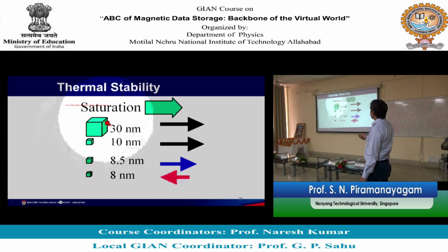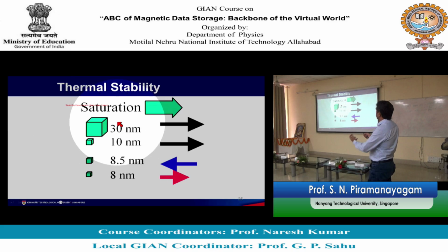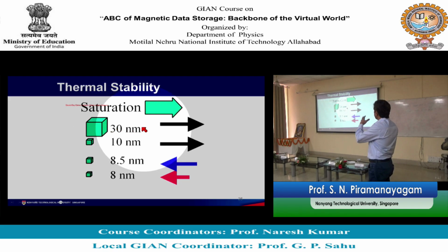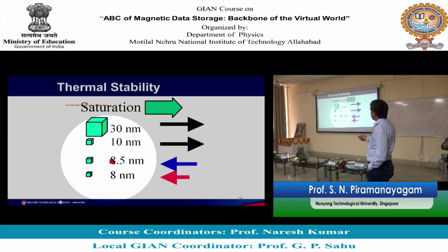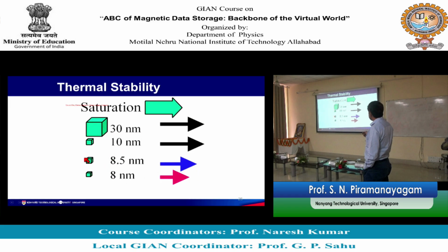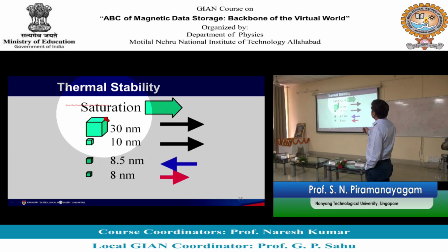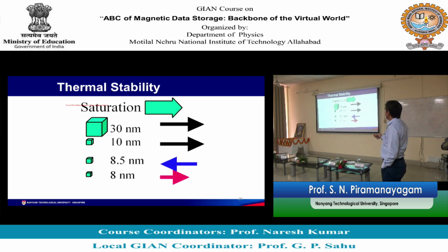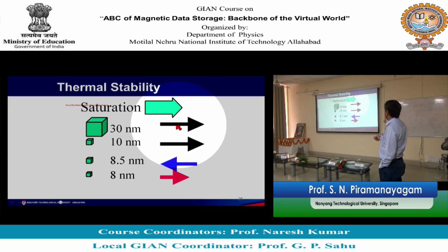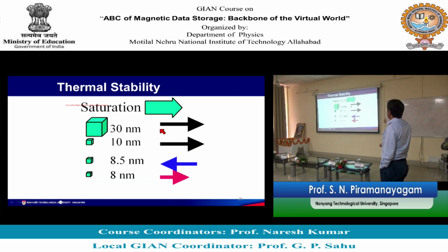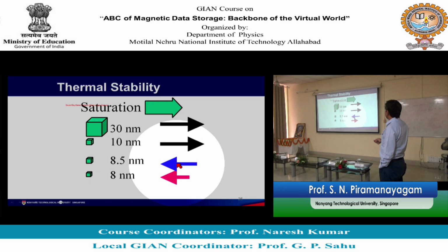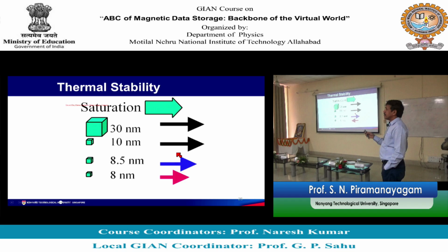So here I have a cobalt cube of 30 nanometer dimension. So length is 30, height is 30, width is 30. So it's a cube of volume 30 times 30 times 30 nanometer cube. And here we have cubes of 10 nanometer, 8.5 nanometer, 8 nanometer, and so on. And I saturate all these cobalt cubes to have magnetization pointing in this direction. Now I look at the magnetization of these 4 cubes. You can notice that the 30 nanometer is retaining the magnetization in this direction. 10 nanometer also no problem. But if you look at the 8 nanometer one, it is rapidly fluctuating. 8.5 nanometer also is fluctuating, but not that rapid. So it is going from left to right once in a while, not that rapid.